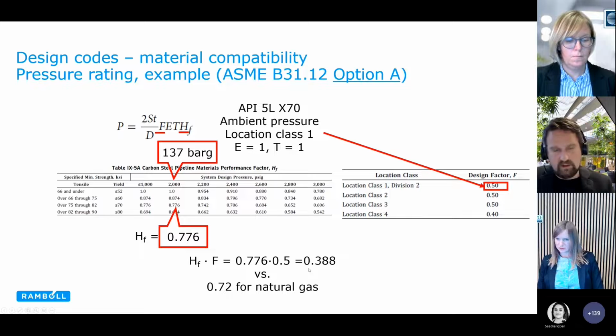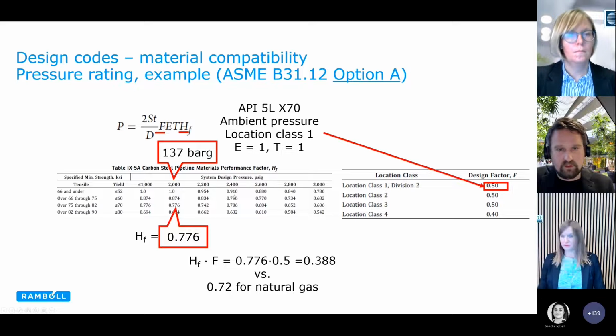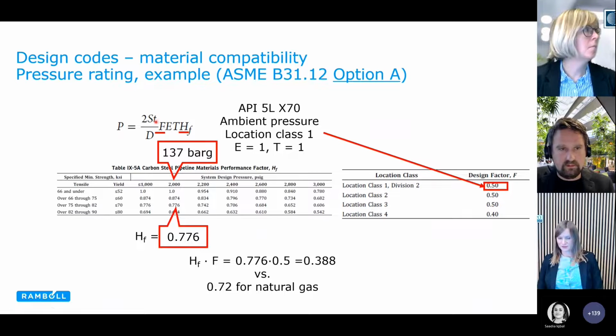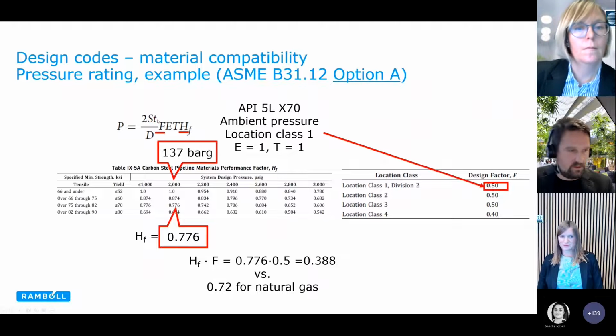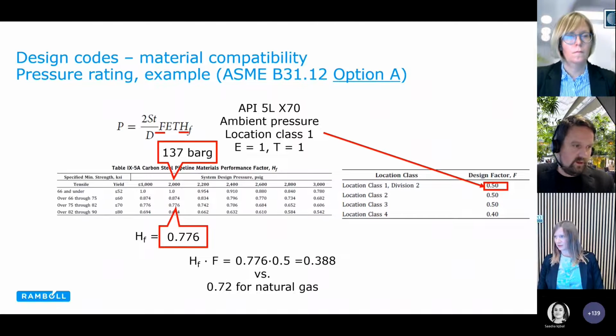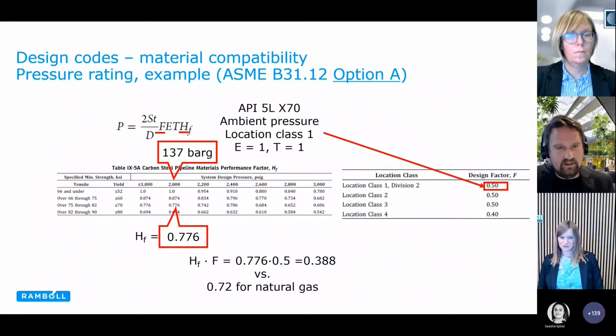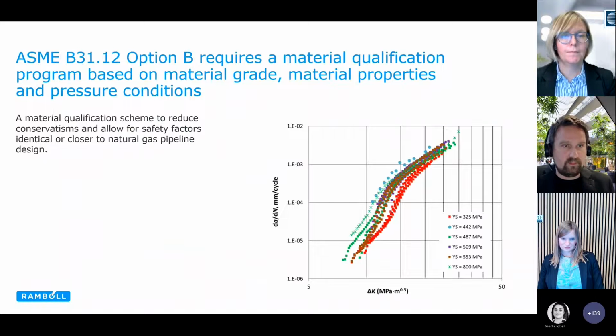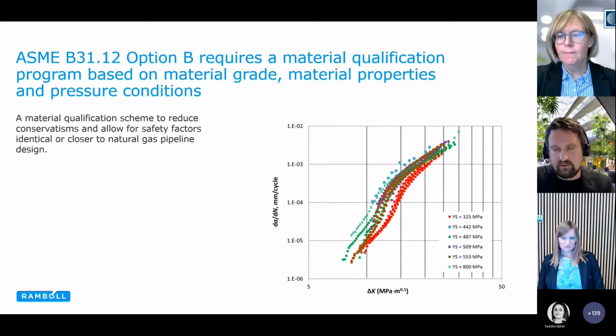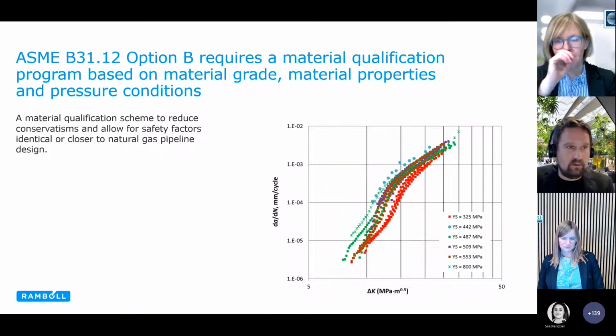So just from the economics of designing a pipeline, this either results in a significantly reduced pressure or a significantly increased wall thickness, which is expensive. And this conservative approach is a little bit debated, because what Ditte was showing you in terms of material data, we're not seeing that large an effect of hydrogen compatibility based on yield strength alone.